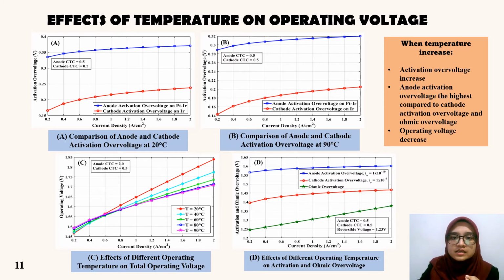Then moving on to figure C, it shows that the value of operating voltage decreased when the temperature increased from 20 degrees Celsius to 90 degrees Celsius, as the voltage drops in the process, which leads to a better performance of the PEM electrolyzer. This is because the increase in temperature causes the electrochemical reactions to become faster, which will increase the value of exchange current density and eventually lead to less voltage drop. While in figure D, the irreversibility in the PEM electrolyzer is contributed by four main voltages, which are anode activation overvoltage, cathode activation overvoltage, ohmic overvoltage, and reversible voltage, but the value of anode activation overvoltage is still the highest, because anode activation overvoltage is the dominant cause of the irreversibility in PEM electrolysis.